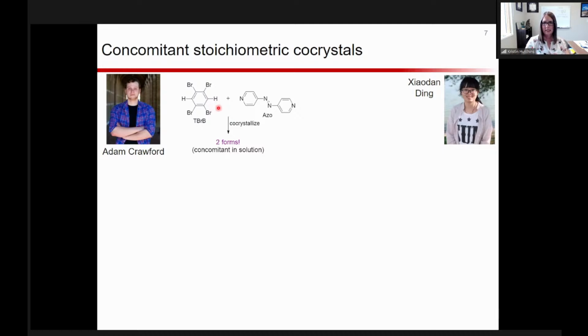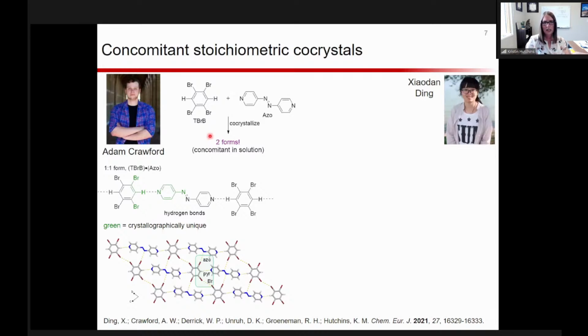And so interestingly, by solution methods, we were actually getting 2 forms crystallizing out concomitantly. And so the first form that we isolated was exactly the form that we expected to get. And so this form is a 1-to-1 form where essentially the 2 components are just held together by CHN hydrogen bonding in an infinite 1-dimensional chain. And so in this case, half of each molecule is crystallographically unique, and the other half is created by symmetry.